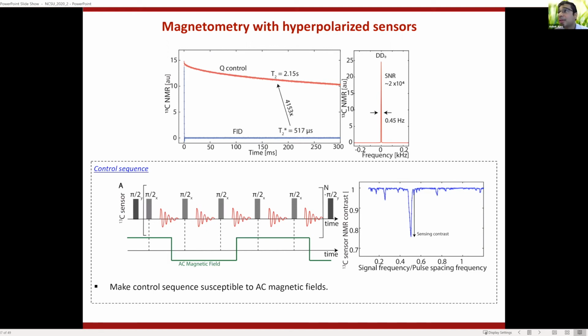It turns out that this has some big advantage over the NV centers in the sense that this carbon-13 is spin half, so it is independent of orientation. And this allows us to make NMR and EPR sensors in nanodiamonds, and these nanodiamonds can be transported physically to a material of interest. And for experts in the audience, it turns out the NV center cannot be used in nanoparticle form as a very good sensor because of this orientation dependence.